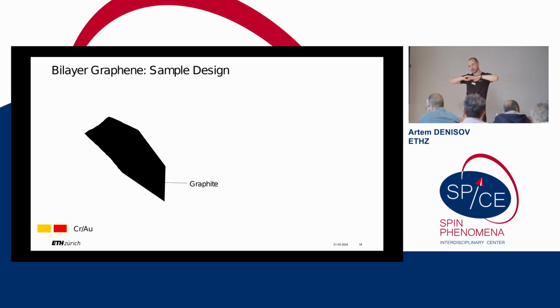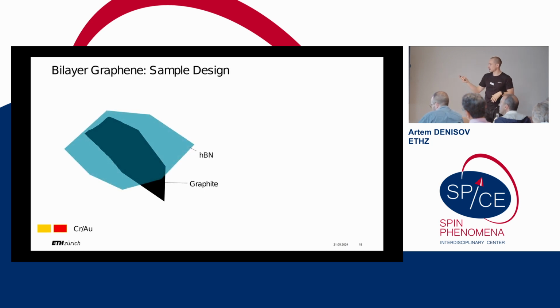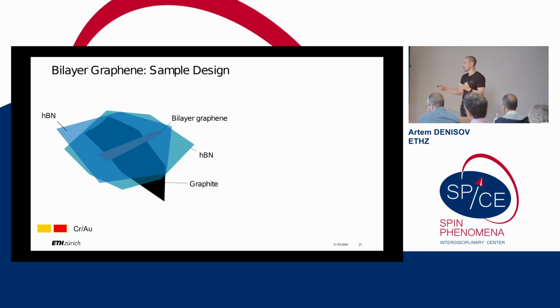Graphite, meaning it's 5 to 20 layers of graphene. And the most important thing is that it should be clean. It should be atomically flat. Because we noticed that if you use some metal or just a silicon substrate for your backgate, it's really hard to open a decent gap in your graphene. Then we use a layer of hBN as the insulator to insulate our backgate from our bilayer graphene flake. And of course, we want some gates on it, so we put another layer of hBN to isolate the bilayer graphene from metal.